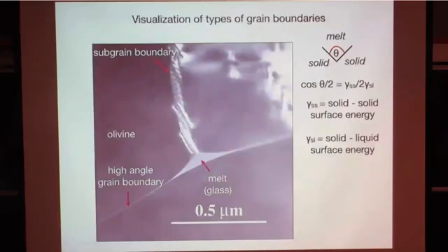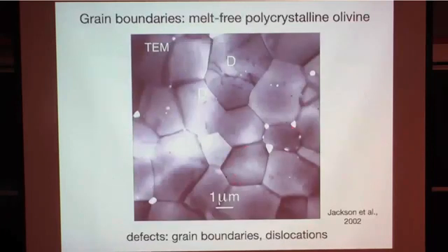But coming back to the melt, the melt distribution is driven by surface energies, right? So the melt will be at every 3-grain edge intersection here. If you had melt in the system, every triple junction here would have melt on it. This is what Laurent actually showed as well. There's melt at every 3-grain edge intersection, whereas these pores occur patchy. There's lots of triple junctions that don't have pores on them.